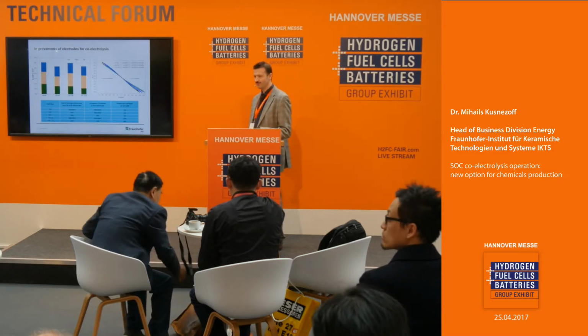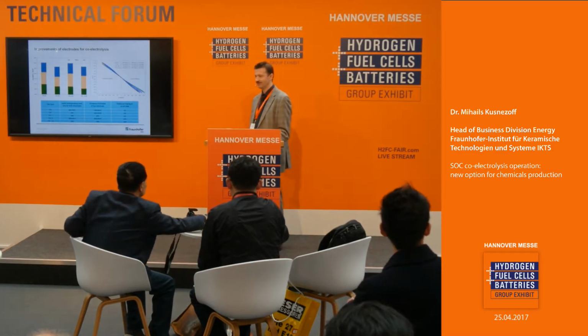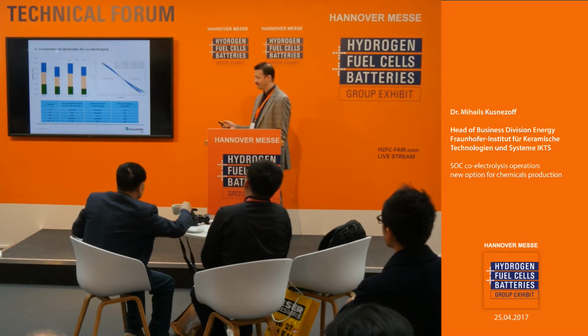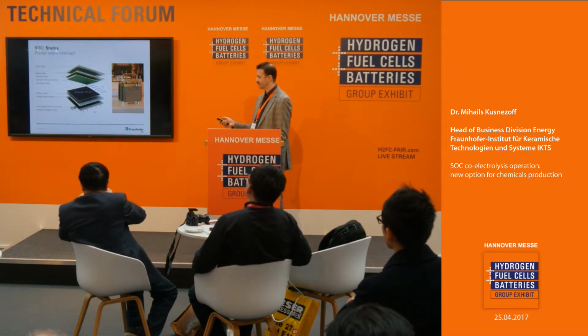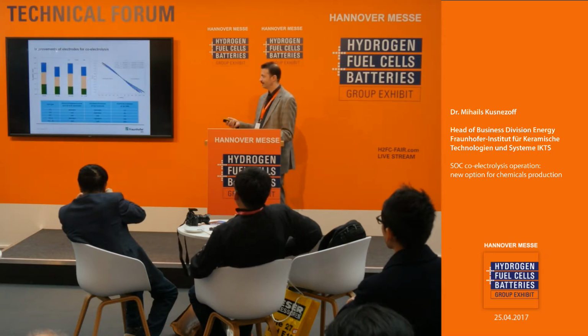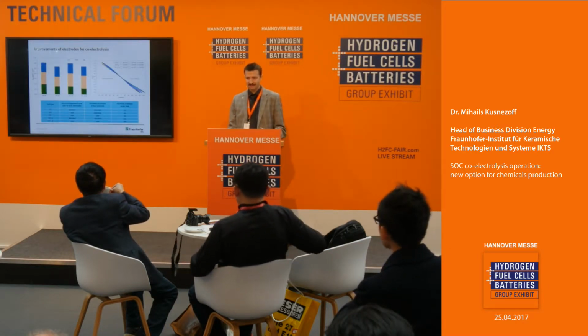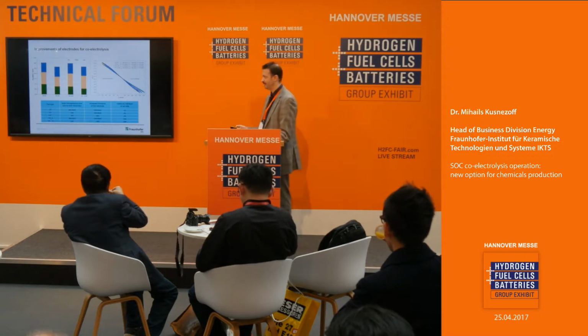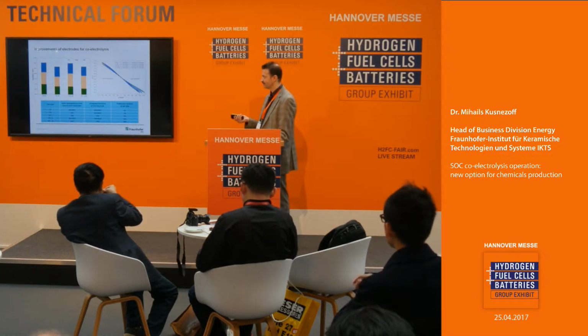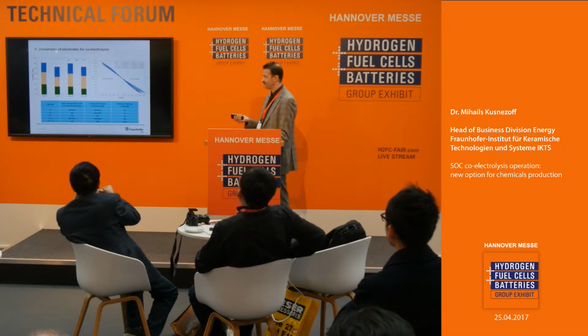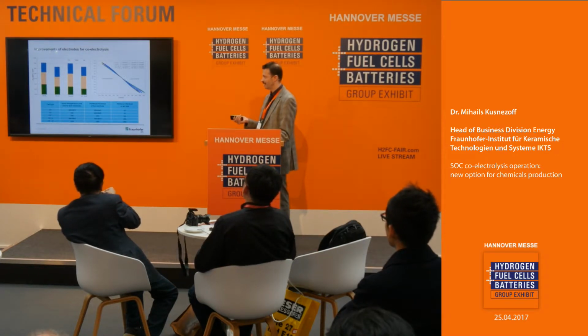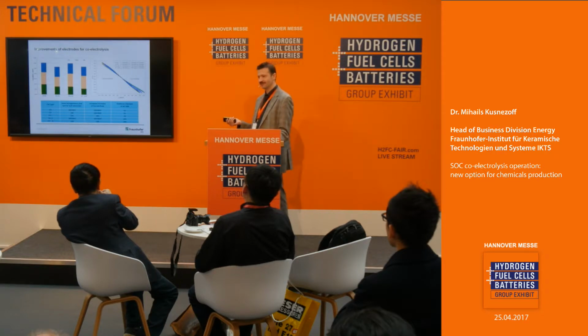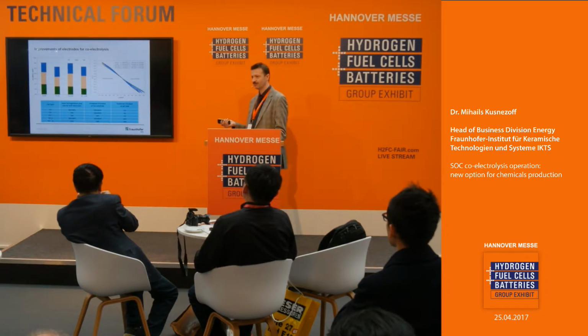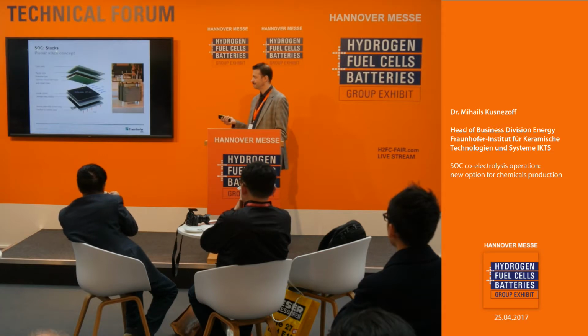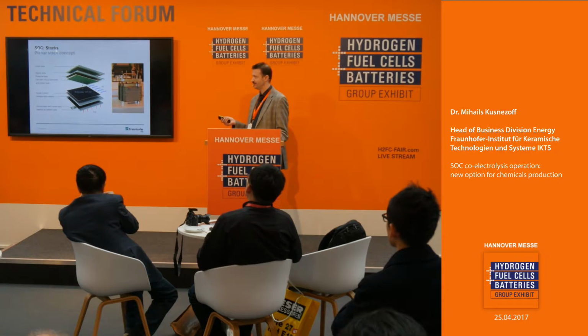So then we have moved from G3 to generation 5 cell, and you see here the basic characteristics of the cell made by impedance spectroscopy. So in G5 cell, we have applied an additional interlayer, and then we have increased the thickness of the fuel electrode and also homogenized the porosity in the fuel electrode. Now we are coming simply to stack performance. So we have tested all these cells also in the stack.